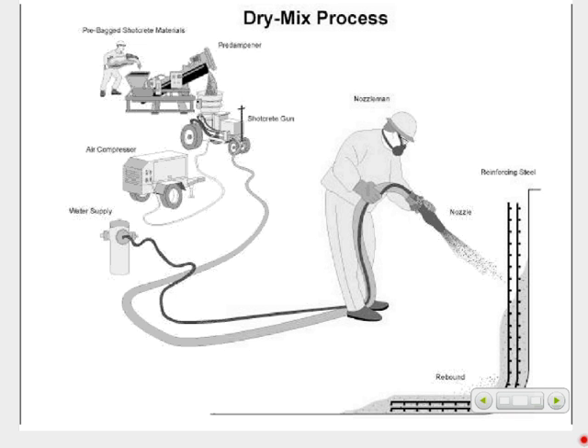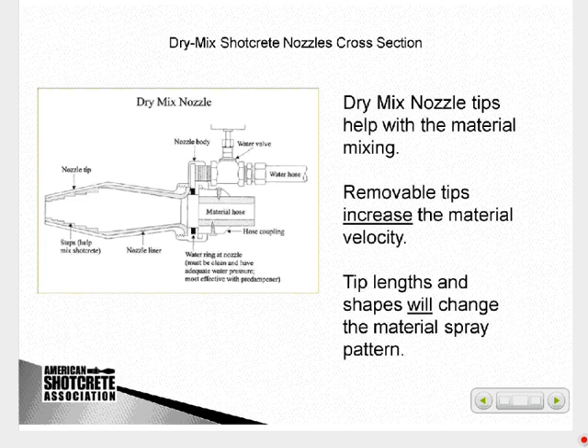So air velocity carries the material all the way through the hose and then adds that velocity as it comes out the nozzle. This is just a cross-section. I won't go into great detail, but it shows you that in the nozzle, the material comes from the right-hand side. Water's injected where you see a nozzle body, water ring we call it, that injects water at high pressure into that material stream of dry sand and cement, sometimes a small coarse aggregate. It goes through the nozzle. It is accelerated by the Venturi effect and mixes. You can see some of the steps that make a rough area inside the nozzle that help to have turbulence that help mix the freshly introduced water to the dry sand and cement or coarse aggregate.